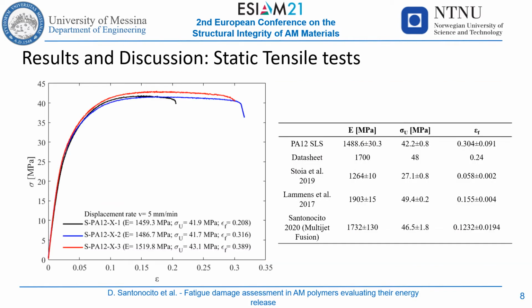Static tensile tests were performed on 3 specimens of PA12 obtained by selective laser sintering process under displacement control. The adoption of an extensometer allowed to obtain the engineering stress-strain curve of the material. The curves exhibit the same trend, with an initial linear elastic part followed by a smooth hardening, where it is not possible to assess in a clear way the yielding point.